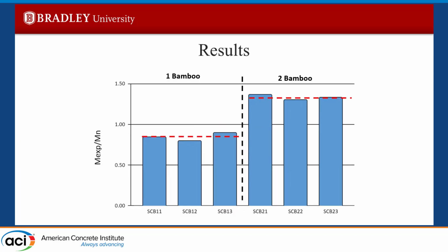And then we have the specimen name on the lower axis, and the experimental moment over nominal moment. We're only focusing on the one bamboo and two bamboo because this research is focused on, is bamboo a good reinforcement for sulfur concrete for planetary applications? So we didn't account for the zero bamboo, but when we got one bamboo, we had an average around 0.85, which means it's not as conservative. But as you can see, as you increase the bamboo, we do jump to a 1.35, which means as you add more bamboo to the sulfur concrete specimens, you will become more conservative, which is what we wanted.